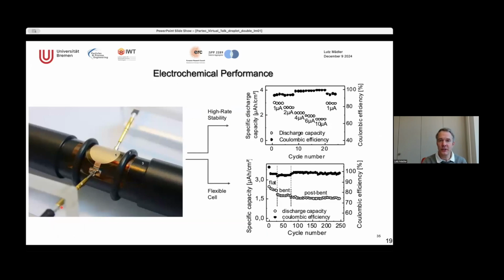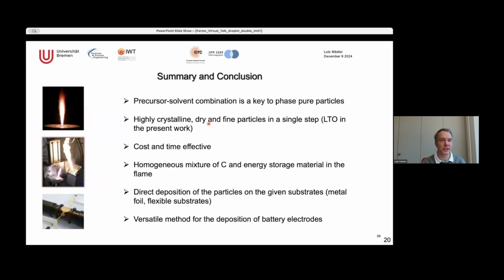And while we bend up and down, here we see that we have some drop in the capacity, but basically it's not breaking. These layers hold and stay intact. And this is because of the porosity and the interlocking of these aggregates we make from the flame, which I find quite fascinating. So I hope I gave you some flavor. I stick here to the battery performance, but I think you could believe me also that we can make this for other applications. So in the end, to bring some take-home messages.